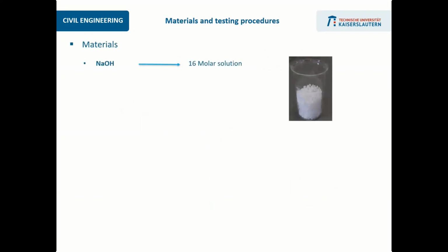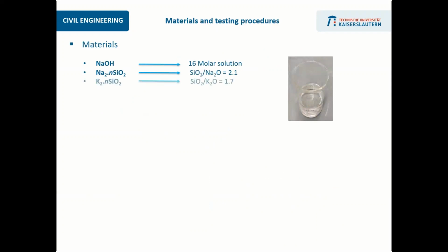The materials used in this study include sodium hydroxide, which was provided by ourselves in 16 molar solution, sodium silicate, which was industrially provided with a molar ratio of 2.1, and potassium silicate, which was also industrially provided, with a molar ratio of 1.7.